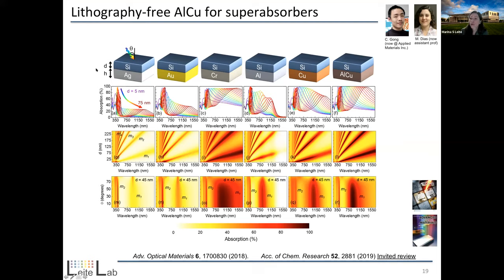So again, I use a scalable approach, no need for nanostructuring anything, by using a bilayer design that is formed by a semiconductor material, silicon, and by the way, this works equally well with gallium arsenide, germanium, et cetera, and a metal back reflector. She decided to look into, one, how much absorption can we have, and two, how much can we tailor the wavelength in which the maximum absorption occurs as a function of the thickness of this semiconductor layer, which is D. There's a second row here showing a lot of data, I realize that, apologies, but it's telling us how much we can shift the wavelength of the maximum absorption as a function of the thickness of the silicon. And what we can see is that the silver and gold work okay, but not so well. Chromium works a lot better.